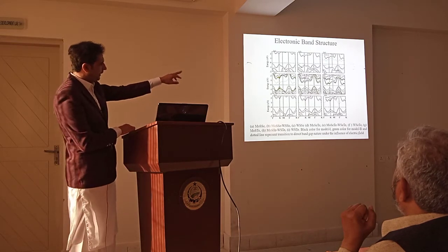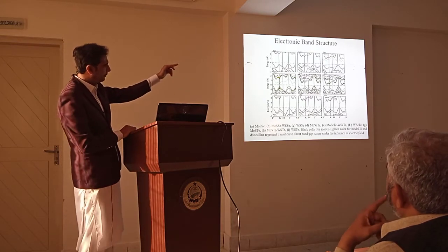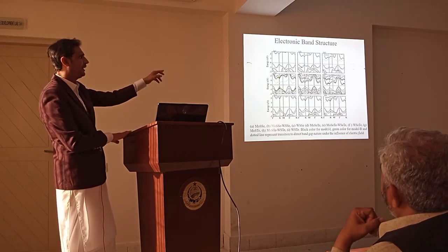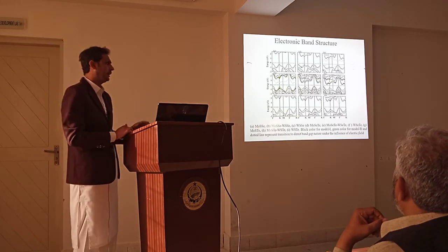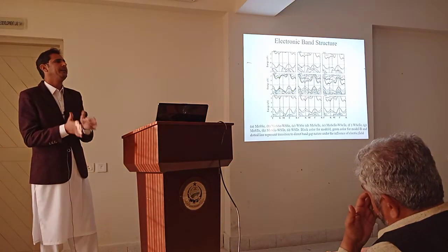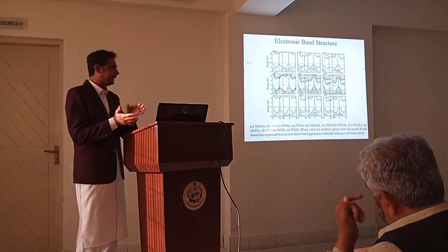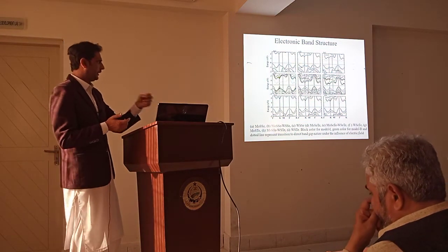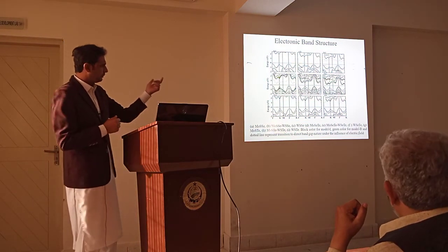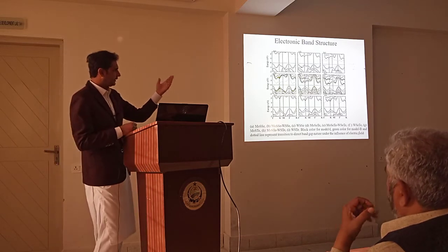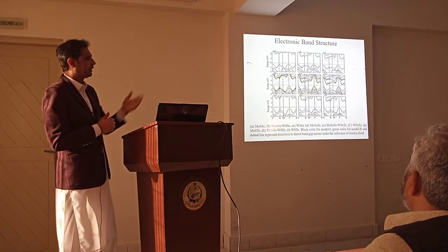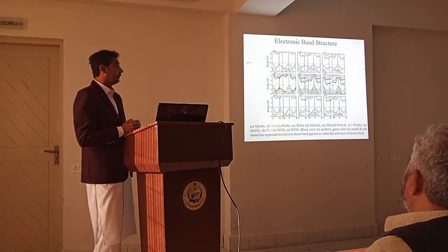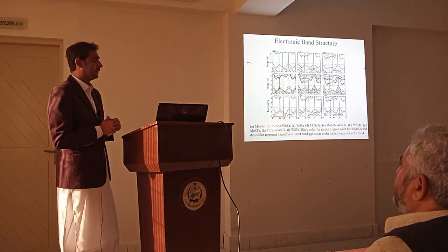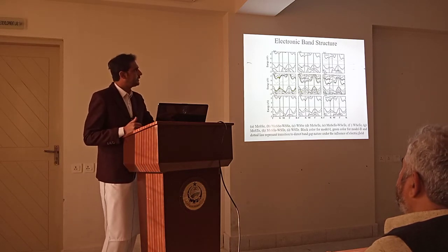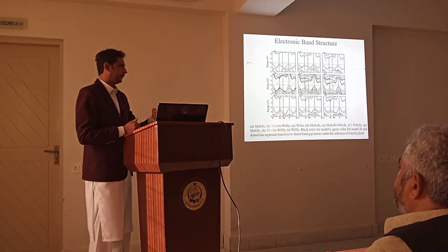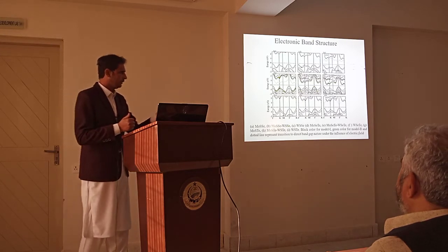Below the Fermi level is the valence band, and above the Fermi level is the conduction band. If we see in A, the conduction band minimum lies at a K point, while the valence band maximum also lies at a K point. It means that VBM and CBM lie at the same K point, so this material has a direct band gap nature. Similarly, in case of B, all these monolayers show direct band nature, whereas, for example, in G this is not direct band nature, so we applied an external electric field, which converted it from indirect to direct.